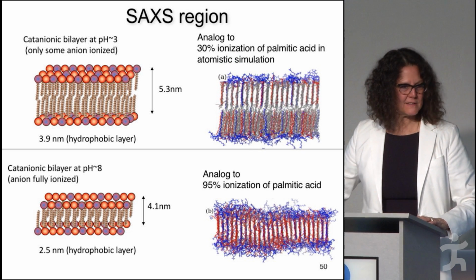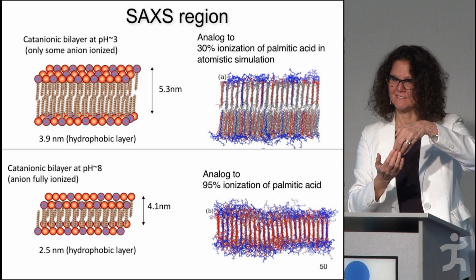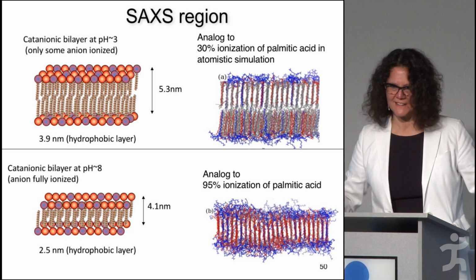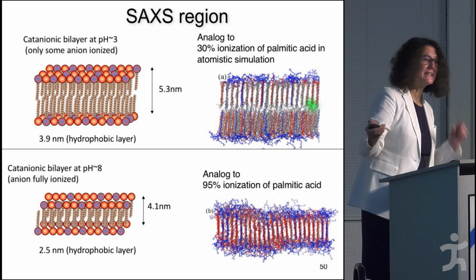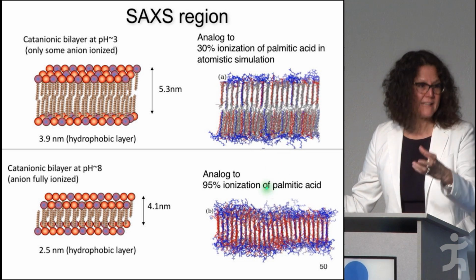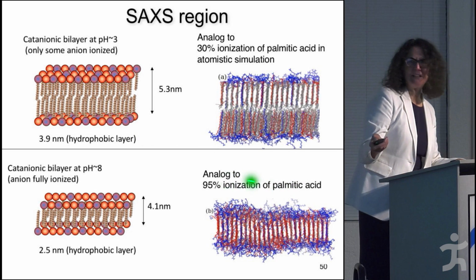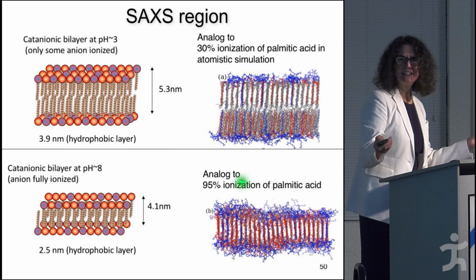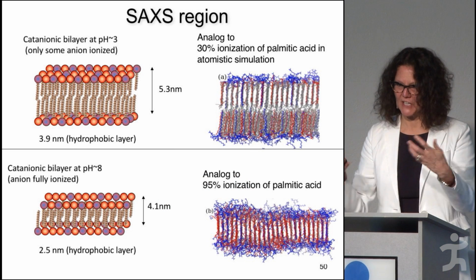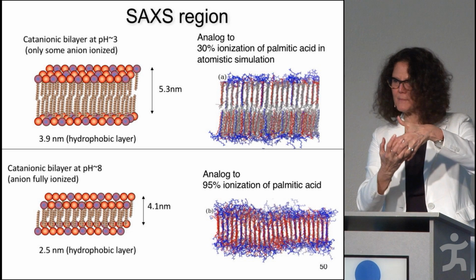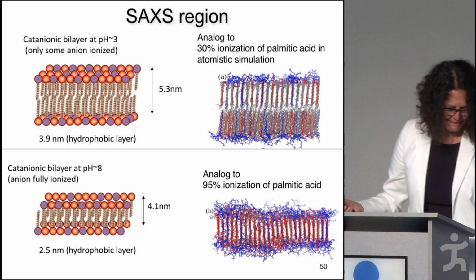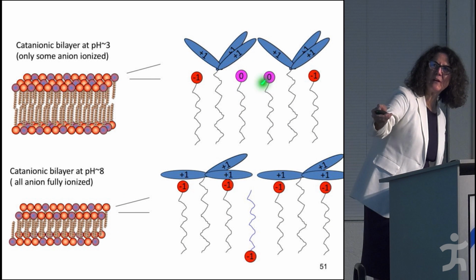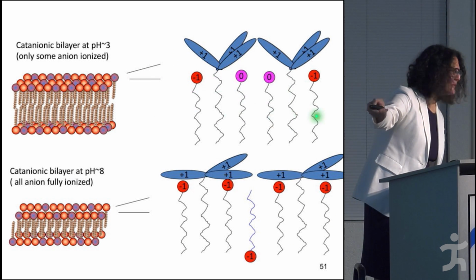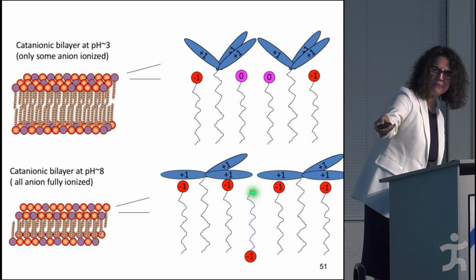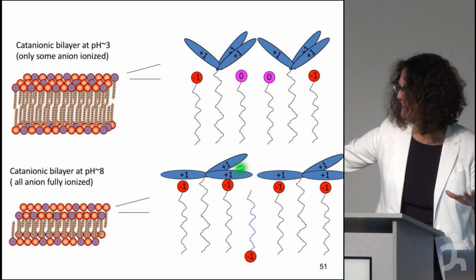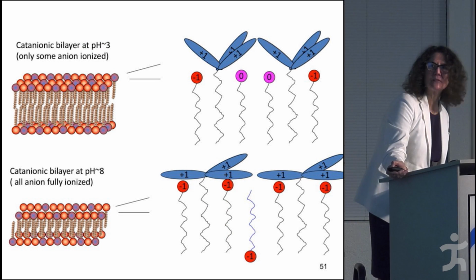So when they are 30% charged, they form a bilayer like I showed you in the beginning, like the normal bilayers that we see in membranes, right? But in a crystalline phase, where you have multivalent ions crystallized in them, or at low temperature. But if they have a pH 8, where you have 95% of them charged, then they overlap like that and collapse the layer. And so basically one can explain that, when you have some fraction without charge, this can sort of go in between. And when you have more charge, they have to lower these big head group charges, and overlap. So what is the relevance of that?